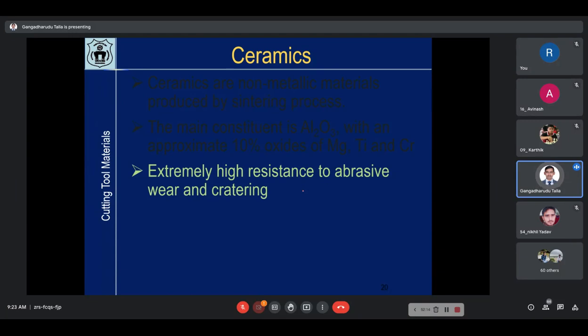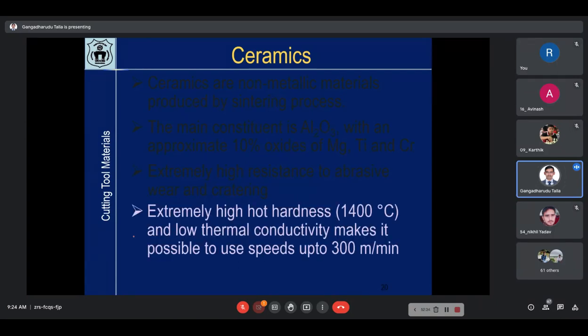Extremely high resistance to abrasive wear and cratering. Because ceramic itself is very hard, and of course it is brittle also at the same time. So its wear resistance is high. Okay. Extremely high hot hardness. Hot hardness you can see up to 1400 degrees Celsius. So these tools can work, and a low thermal conductivity makes it possible to use speeds up to 300 meters per minute. So here speed has increased further.